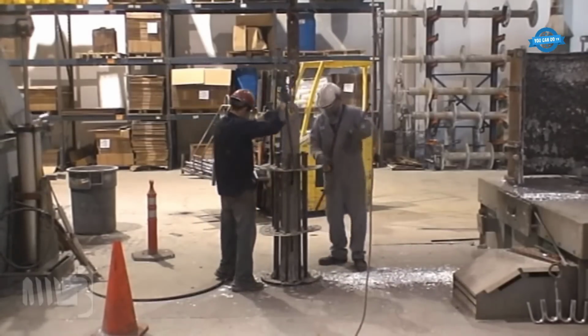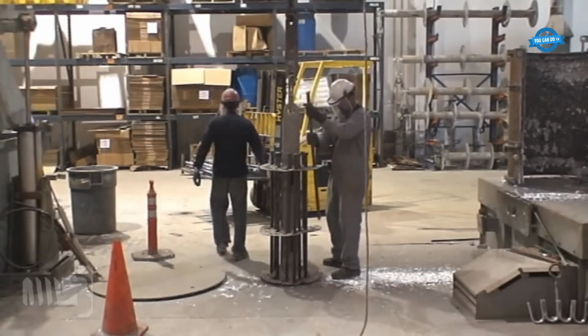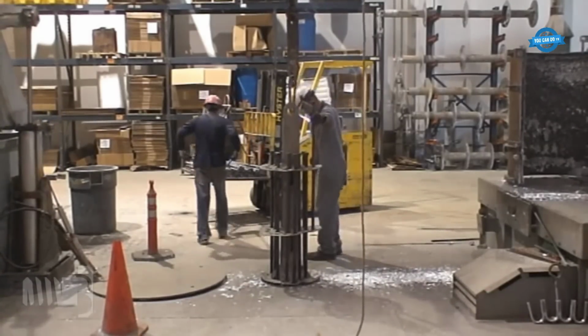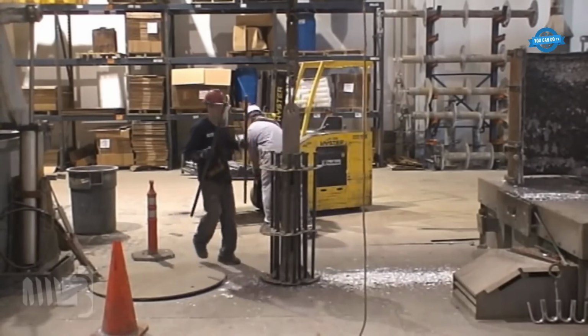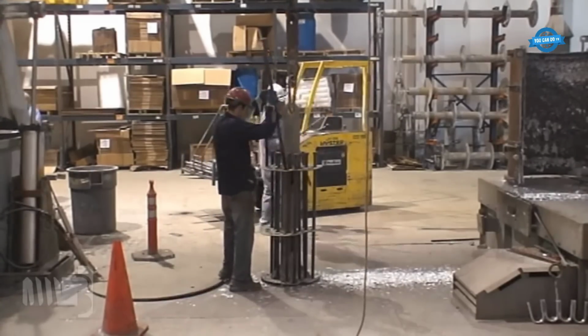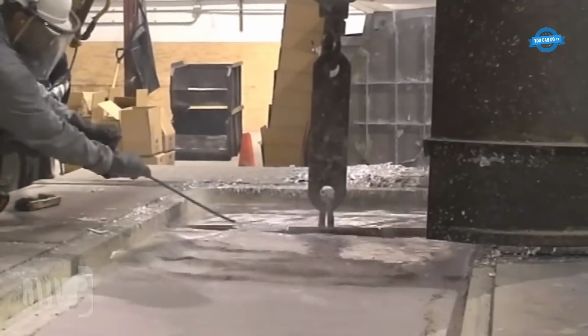After pickling, bolts are placed in racks and lowered into a 12-foot long by 4-foot wide by 7-foot deep tank of 840-degree molten zinc. The bolts remain in the zinc for between 2 to 4 minutes. When the bolts are removed from the zinc, they are spun in a high-speed centrifuge to remove excess zinc from the threads.